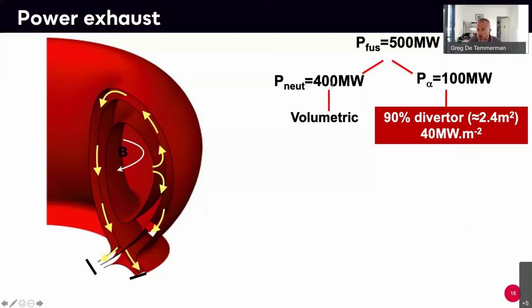400 megawatts is in the form of neutrons. 80% of the energy of the reaction is actually in the form of neutrons. Those neutrons are not charged, so they get out of the plasma and they just deposit that energy around the machine. So that's fine. It's a volumetric process. It doesn't put much heat onto the components. Typically, in a fusion reactor, you would have half a megawatt per square meter in terms of volumetric heat, so it's not that much. In terms of helium particles, they are charged.